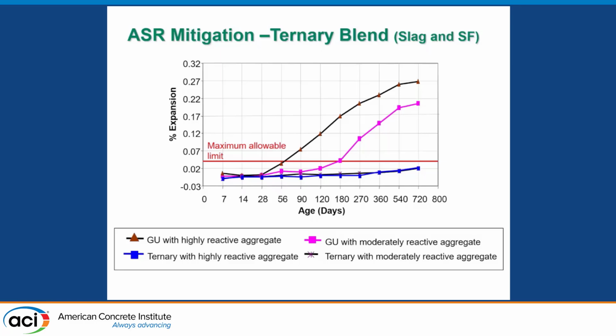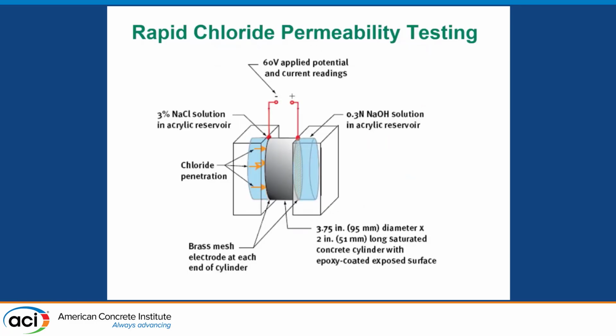So when you start using blends, it really helps you when you have areas where you're concerned about ASR, or you may have other moderately aggressive soils or other aggregates that are reactive. Certainly when we did this study, we also looked at rapid chloride permeability.